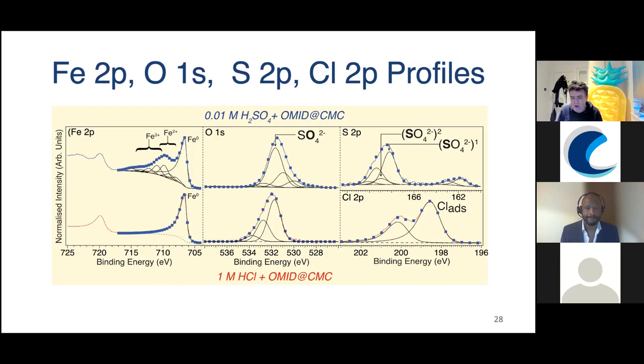For instance, to do the OMID on the hydrochloric acid, to get the state of the molecule, this took over a year to realize it was these two singly protonated species. It sounds very simple, well, relatively simple when I talk about it. We didn't realize there was five peaks. You can also fit that with three peaks in a consistent fashion, but we didn't understand that. It was only, which I didn't explain here, that we also measured the head group, a thick layer of the head group, to get some idea of the XPS from that, and then transfer that knowledge to this system.